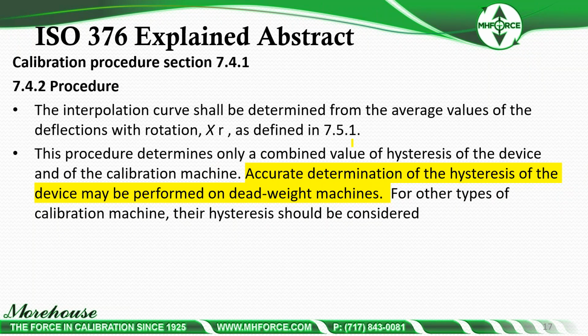For 7.4.2, the interpolation curve shall be determined from the average of deflections with rotation XR as defined in 7.5.1. So if we look at 7.5.1, that's basically going to tell us that we can use a first, second, or third order equation. And that's important to note because other standards allow higher order equations, where ISO limits it per that section to just a 3rd degree only.